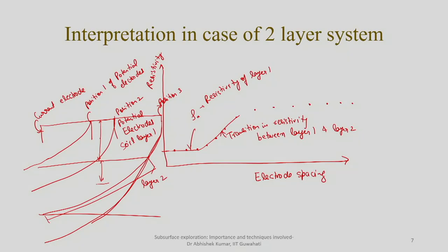So, there will be a transition sooner with respect to the electrode spacing increase. The resistance offered by the material is clearly giving an indication that the majority of the content you are getting is from layer number 2. So, this you can call rho 2, this is rho 1, resistance offered, resistivity of layer 2.